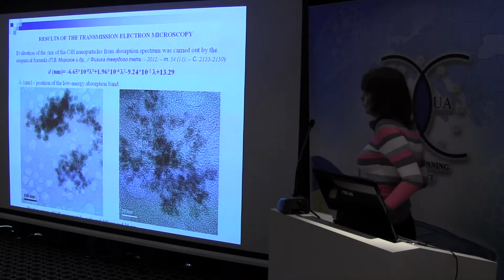Evaluation of the size of cadmium sulfide nanoparticles from the absorption spectrum was carried out by the empirical formula, which you can see on this slide. And we established in our experiment that the size of these semiconductor nanocrystals was in the range from 5 to 8 nanometers.